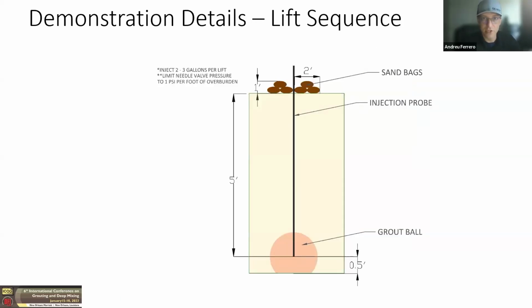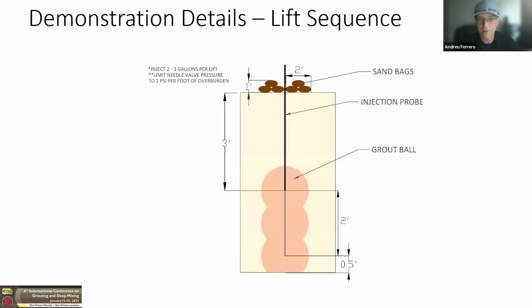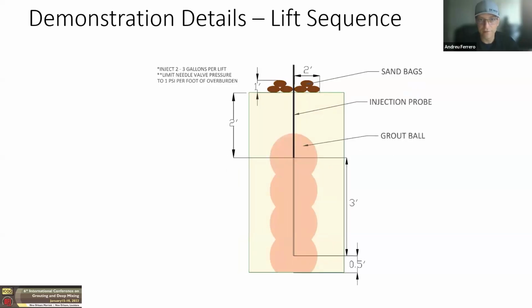This is the injection lift sequence. So we drive the probes down to within about 6 inches of the bottom, and then we inject the first lift, followed by the second lift, the third lift, and the fourth lift, making sure that we leave at least a couple of feet of overburden with an additional overburden pressure of some sandbags to prevent any kind of heaving or chimneying of the material up around the grout probe itself. The intention here is to create a grid that these grout columns stacked up on top of each other will interlace and create a solid treatment area.